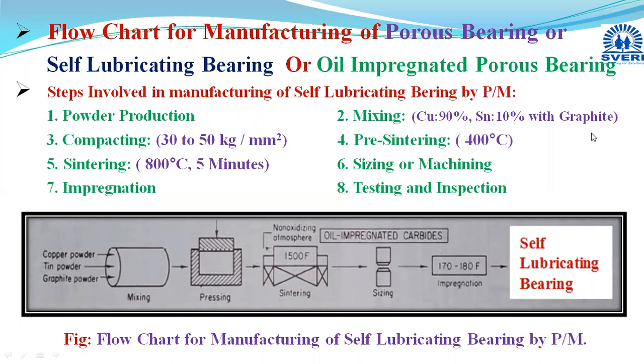this graphite. So in the second stage, we have collected copper and tin, along with a very small amount of graphite. Here a 90:10 ratio is taken for copper and tin, and a very small amount of graphite is collected, and a uniform and homogeneous mixture is obtained. In this mixing process, we can use different blenders or mixing devices like a Y-cone blender, double cone blender, blade mixer, screw mixer, or rotating drum. With the help of these devices, we are able to obtain a uniform and homogeneous mixture of this copper, tin, and graphite.